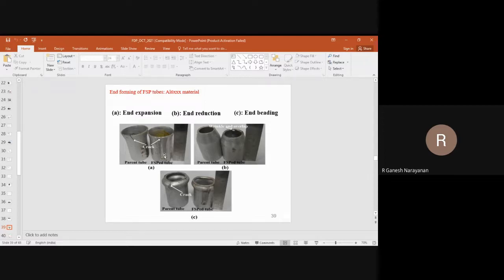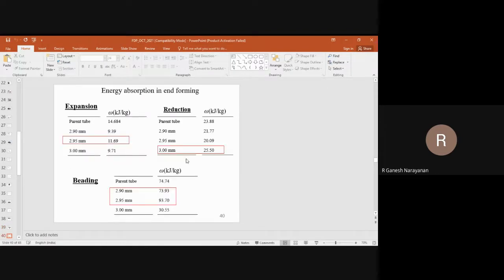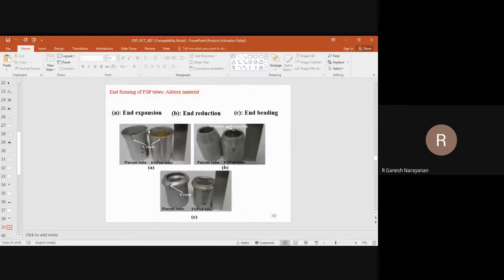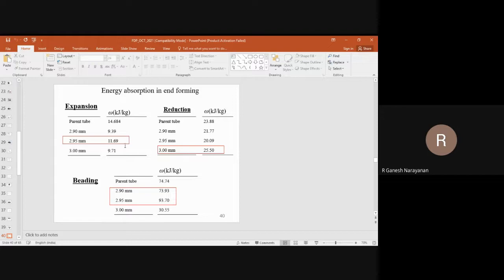So the overall weight reduction is possible. Which welding are you going to use? You can use friction stir welding. And again, you can go for such manufacturing processes like end forming: expansion, reduction, beading. While doing so, it has been found that the energy absorption during this quasi-static end forming of these welded blanks or the processed ones can be at par with the parent tube. Some examples are given here.